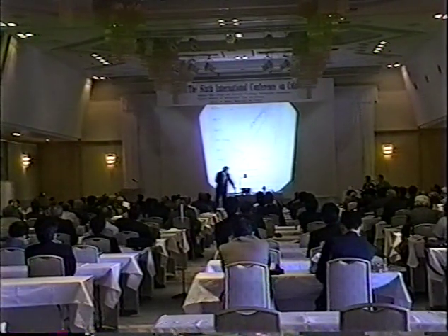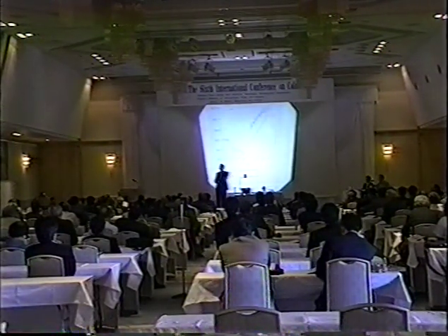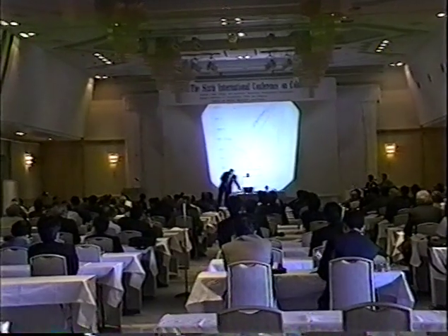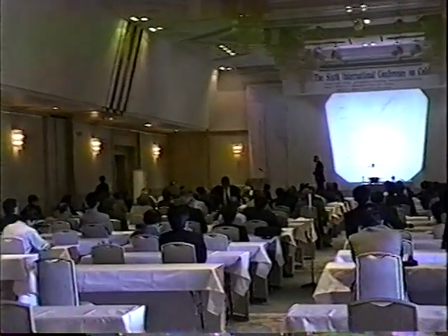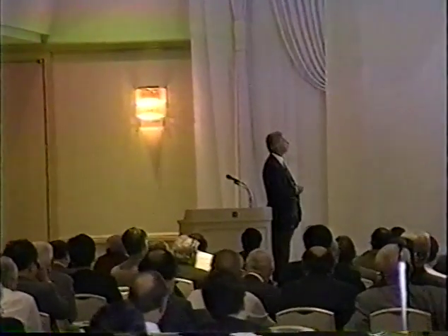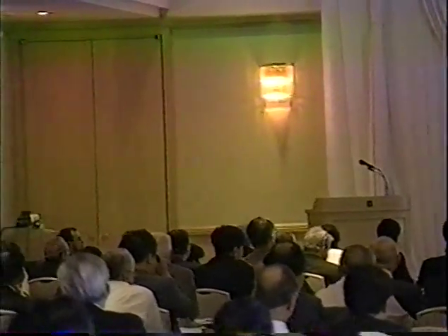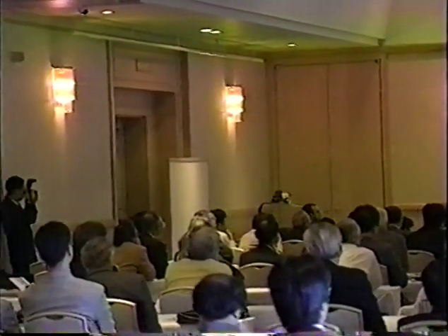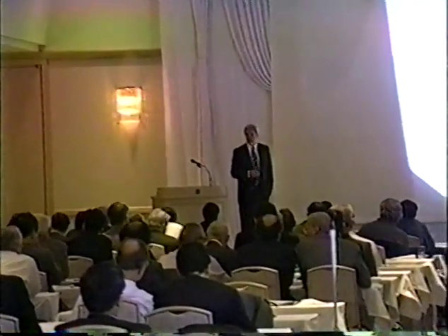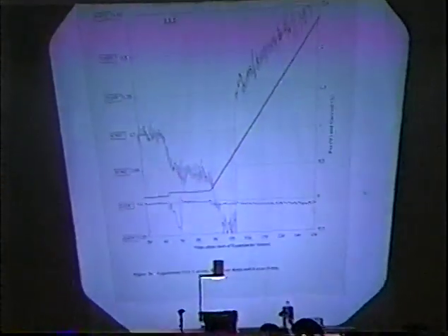We observed the same behavior as you. By increasing the current, sometimes the loading decreases. Do you think that the bubble formation for a particular configuration can affect the electric field configuration in producing this effect? Well, we are not really able to observe the cathodes at the times that they're doing this, but a conjecture is that the high loadings are obtained only because a surface film of a particular structure has been formed on the surface.